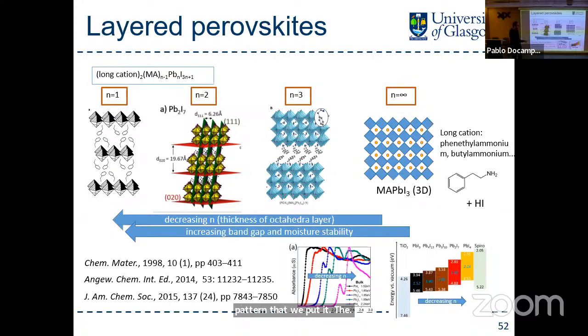And the properties change. The more you confine it, the more it looks like a single layer, the more your exciton binding increases. So it's harder to break off those excitons, and then your device physics becomes dominated by exciton dynamics, not free charge, which is what we have with the perovskite. Now, when you make devices out of these, they don't work very well. Charge transfer is not fantastic with these, because normally you'd have charge transfer going in that direction, and you've got that insulating layer in the middle. It doesn't make your device better when you do that.